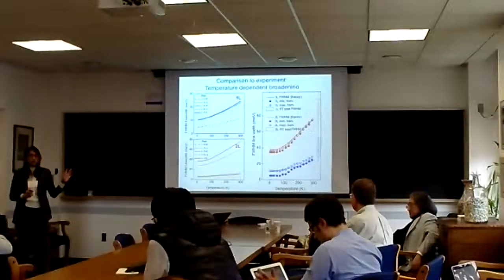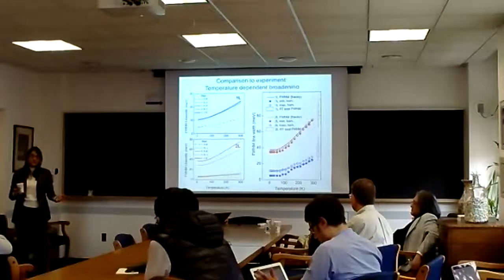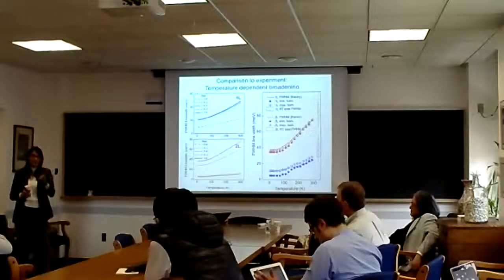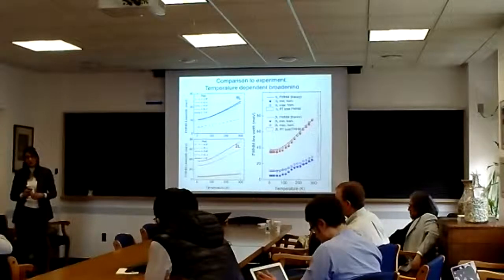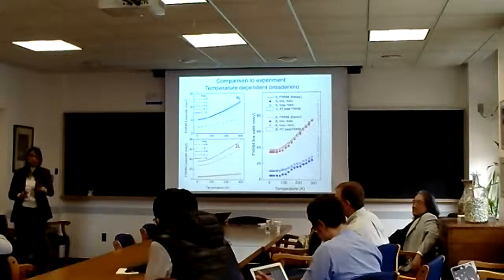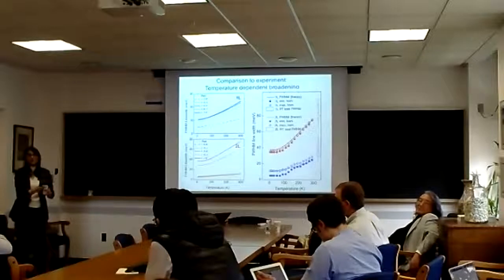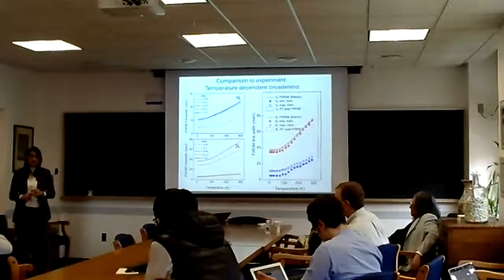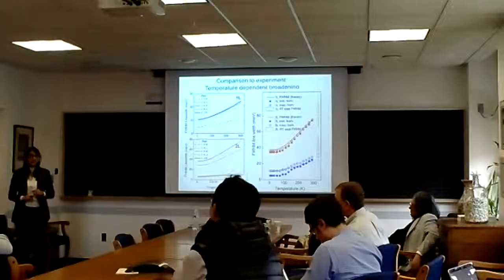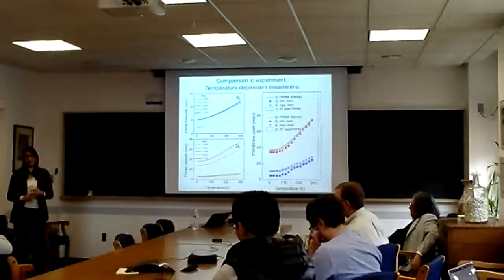And one of the reasons I chose tungsten for most of my talk was because the spin-orbit splitting is large, and I could observe the excited states comfortably. Even at room temperature, I could see a big sharp peak in the middle, which you can't do when you have the smaller spin-orbit splitting. So it was a choice of material for practical reasons as well. But definitely there are a lot of interesting things to do with the dark state, and people are looking at modes that go in the plane of the material itself. It's just something that I didn't work on here.